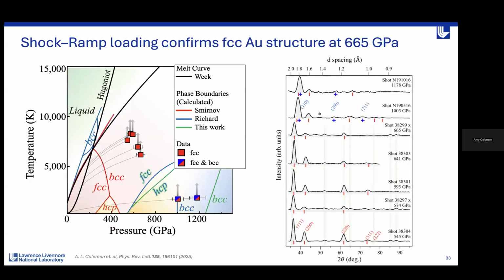To cut a long story short, we'll come to the results of this gold paper. On the left-hand side, I've got a phase diagram. It's a very messy phase diagram because I've included all of the predicted phase boundaries. There's the red boundaries which show this predicted BCC transition at 400 GPa, and these blue phase boundaries that predict FCC is stable until much higher pressures.